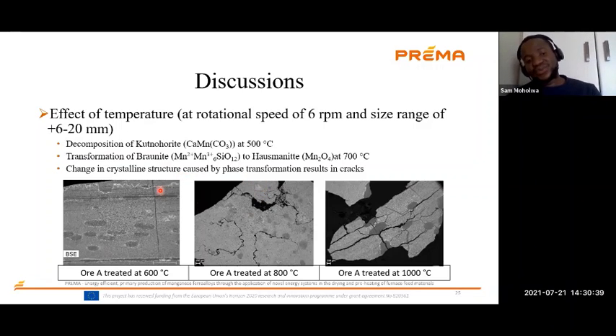Then one other thing you need to know is that Braunite and Hausmannite have different crystalline structures, which means that if you have Braunite transforming into Hausmannite, you have a certain mineral transforming into the other. You have a change in crystalline structure from one structure to another, meaning that there is a volumetric change when these minerals transform, when Braunite transforms into Hausmannite. This mineral change is responsible for the formation of these cracks.